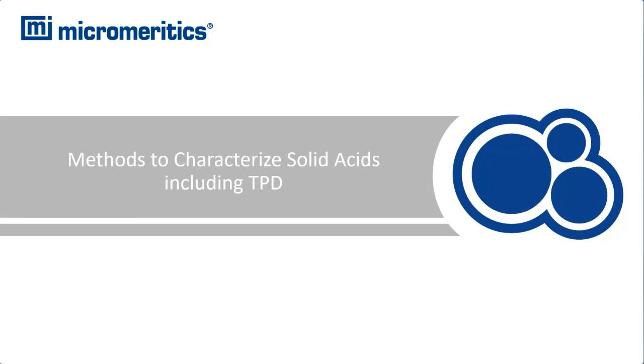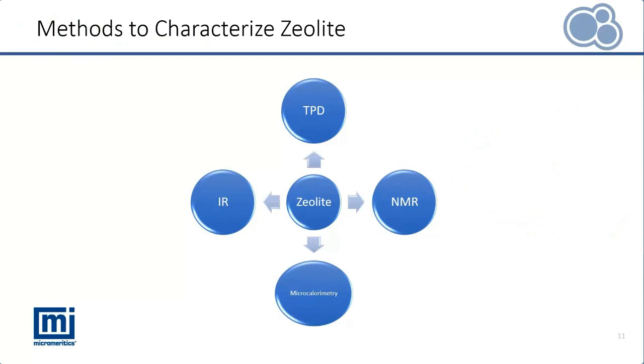Different techniques have been developed to characterize the acid sites. The most commonly used techniques are TPD, NMR, and IR spectroscopy. We can obtain information on the total acidity of a solid material, heat of desorption, and Bronsted acid site concentration using TPD. With NMR spectroscopy, we can quantitatively determine the concentrations of acidic sites and also qualitatively differentiate Lewis and Bronsted sites. Infrared spectroscopy can distinguish Bronsted and Lewis sites — pyridine is often used as the probe, where the pyridinium ion adsorbs onto the Bronsted site but coordinatively bonds to Lewis acid sites, resulting in different vibration frequencies to differentiate the two.